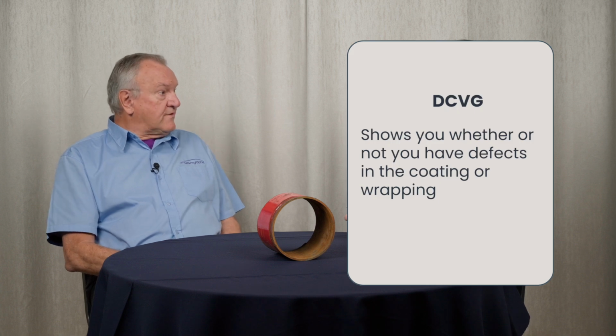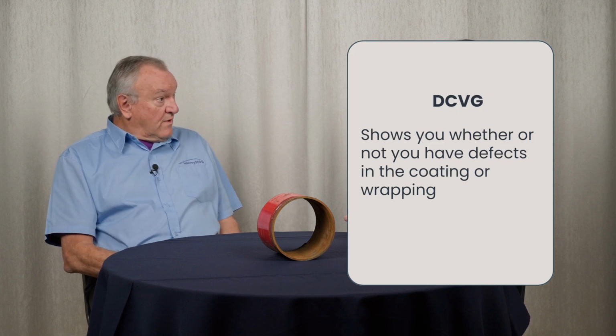And the DCVG survey, its primary function is to show you whether you have defects in the coating or wrapping system. They could be mechanical defects that were caused during laying of the pipeline. It could be caused by degradation of the wrapping over time. It could be caused by roots penetrating the pipeline coating, for example. Some of the old pipeline coatings, like bitumen, for example, the roots are susceptible to damage. This damage then exposes the steel of the pipeline.